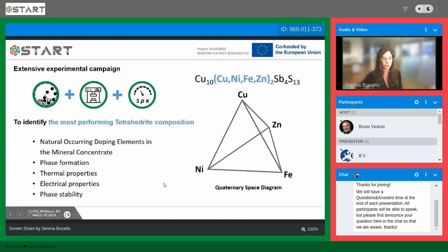Okay, so then we go to this part, where I will explain how practically in the START project we use mechanical alloying and tetrahedrites. So we performed a very extensive experimental campaign using ball milling at lab scale, sintering, and measurement of the thermoelectric properties to identify the most performing tetrahedrite composition in terms of transition metal dopants that substitute at the copper sites. Taking into consideration many factors, among them the doping elements already present in the mineral concentrates, the phase formations, the thermal properties, electrical properties, and the stability of the tetrahedrite phase with these substituents.